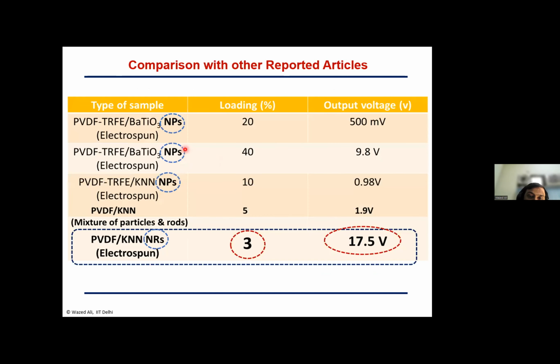These are some comparisons, whatever we have done in the research work as compared to other reported research work along with barium titanate and all, and KNN, of course, electrospun. But in our approach, 3% loading, which is basically the nanorods. Nanorods, as I mentioned, is giving the highest property as compared to particles, and we could harvest up to 17.5 volt, with only 3% loading in the electrospun fiber. The loading is very, very less as compared to the other reported values.